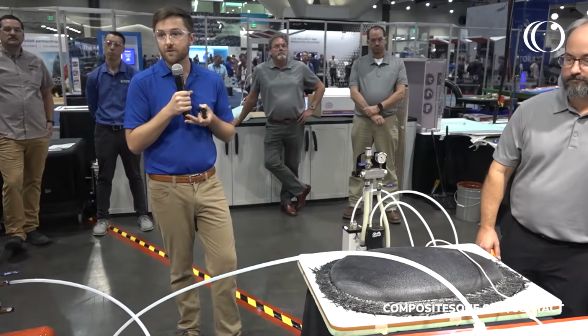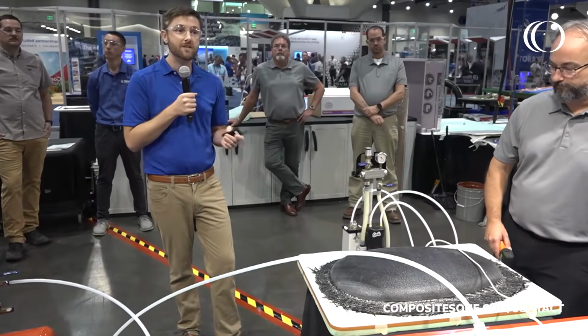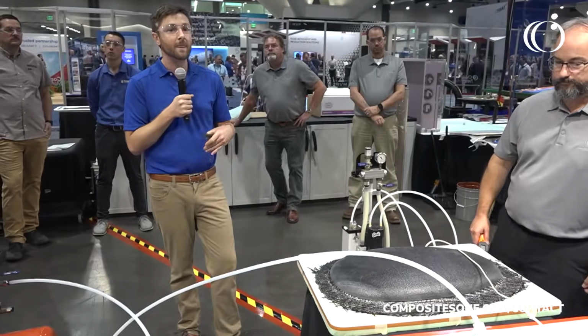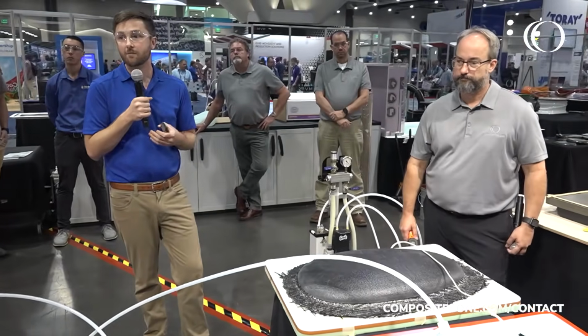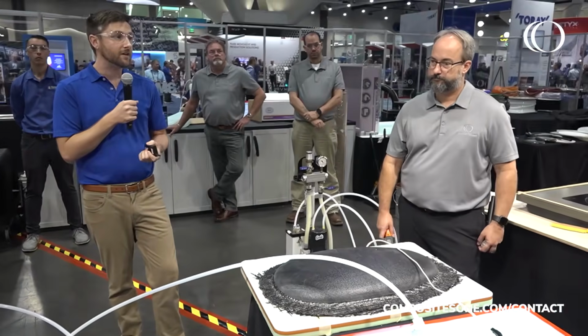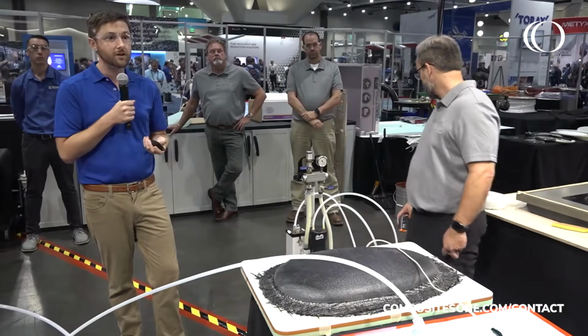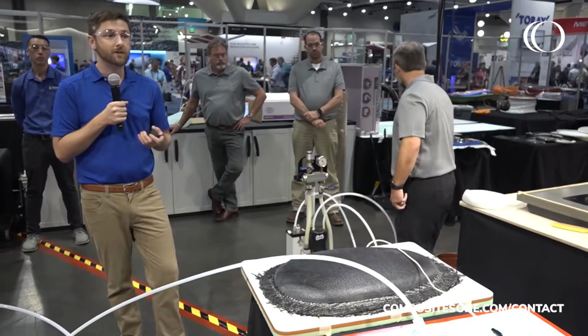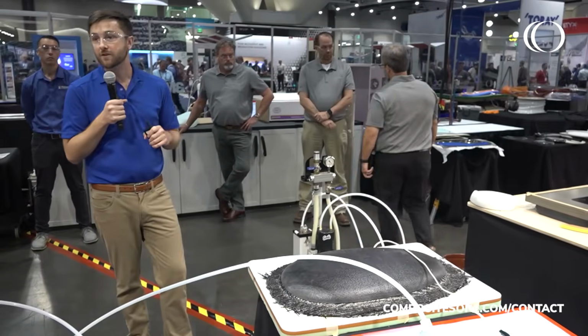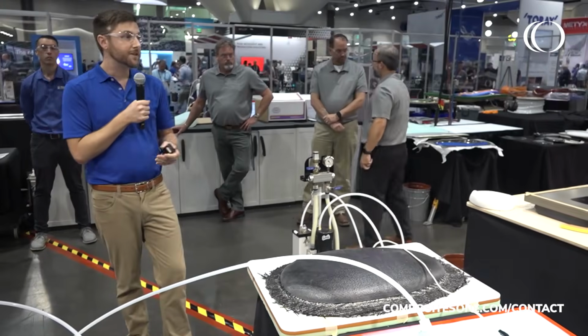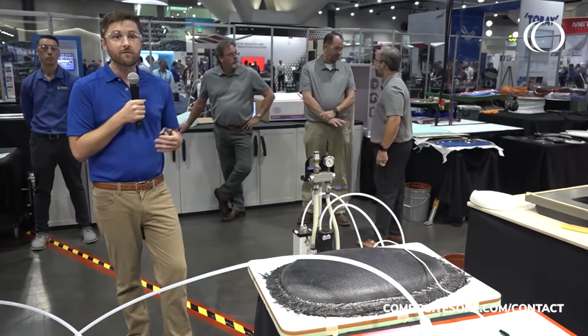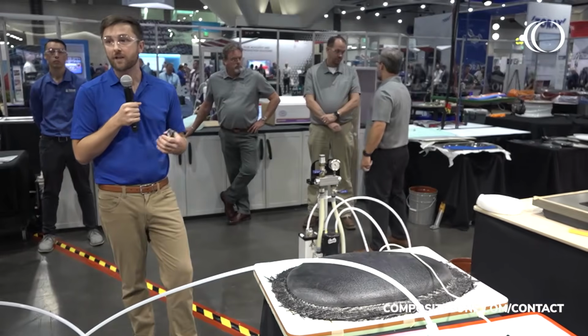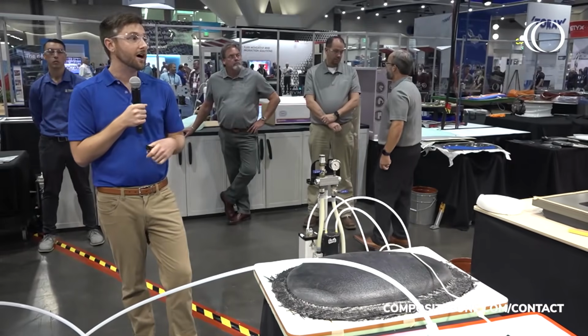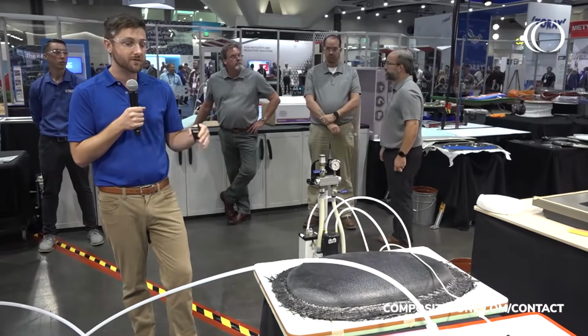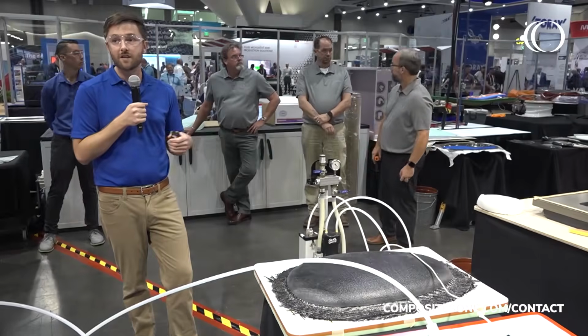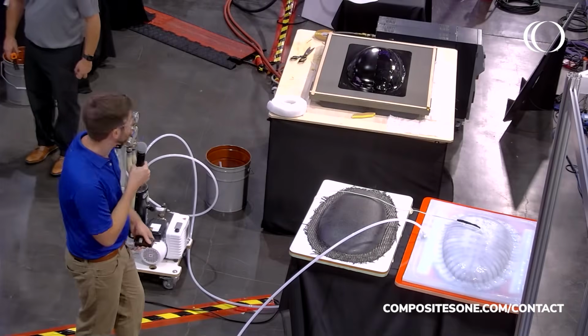Standard product Qisos are offered from about 270 GSM up to 1100 GSM, and then we can customize really anywhere in between. If there's a particular areal weight you're looking for or a particular cured ply thickness, we can right-size the product to be exactly what you want in terms of thickness, but also in terms of width. So if you need an 18-inch wide ply, we can produce the Qiso at 18 inches, and that helps to cut down on scrap associated with cutting your plies and any scrap on the edges.